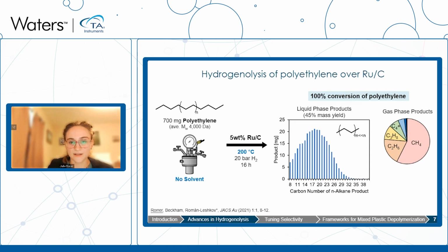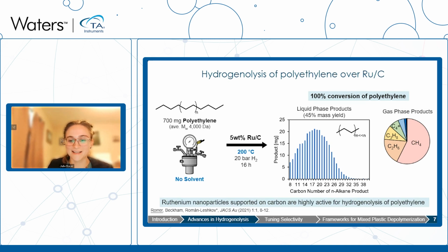The liquid products are a 45% mass yield of linear alkanes with carbon numbers ranging from C8 to around C30. And our gaseous products are primarily methane with some other light alkanes, including ethane, propane, and butane as well. And this is a very exciting process because we can see that this is done at only 200 degrees C. Compared to the 400 to 900 degrees C for pyrolysis and gasification, this is a much milder conversion.